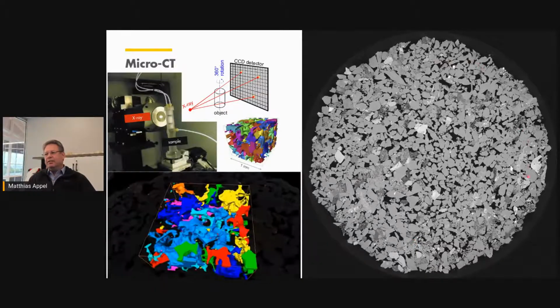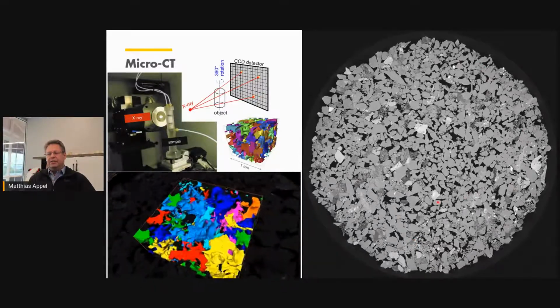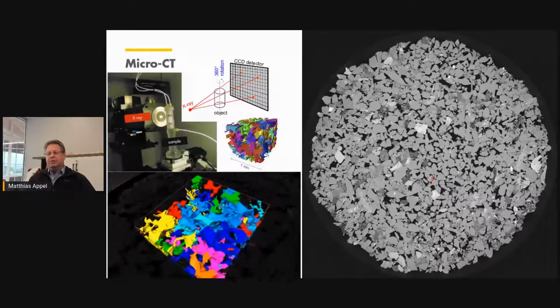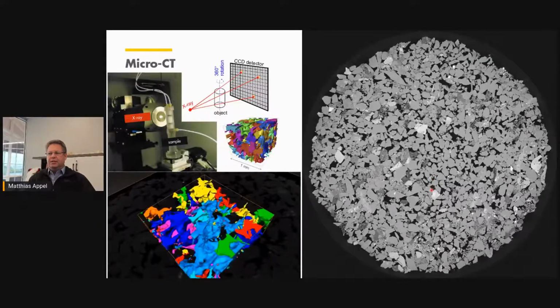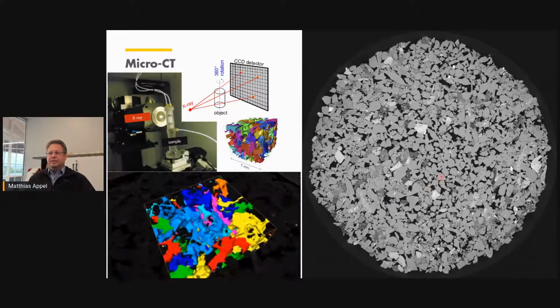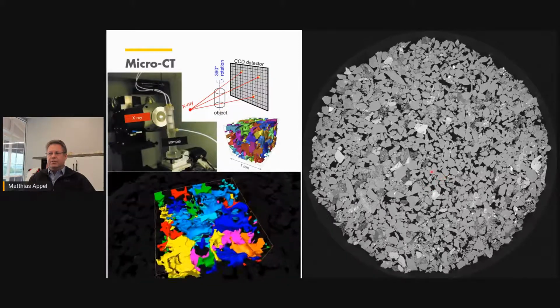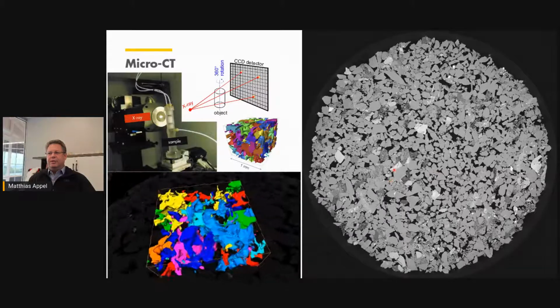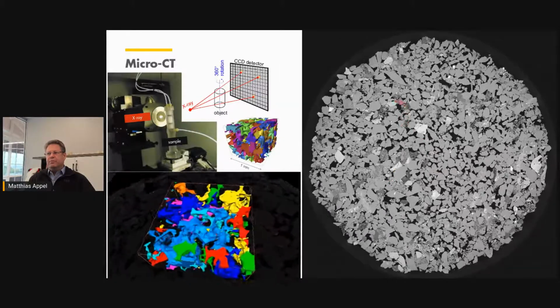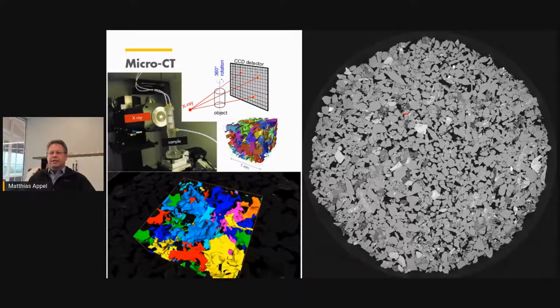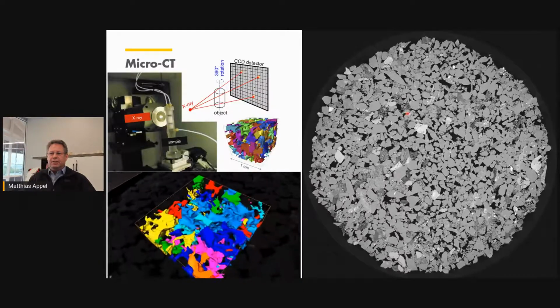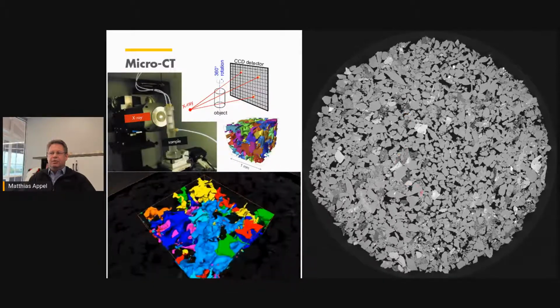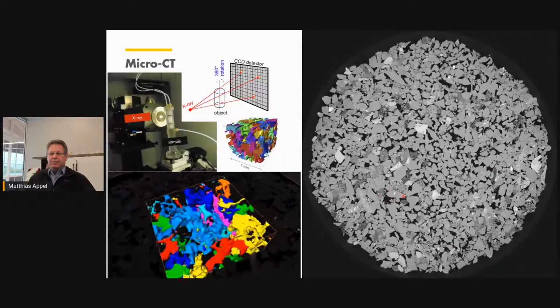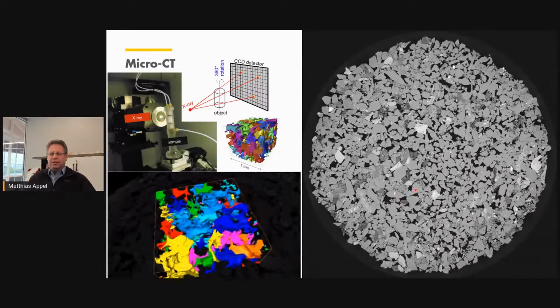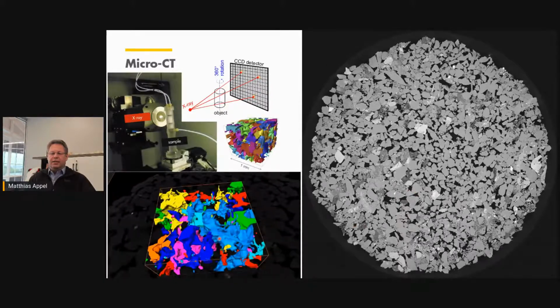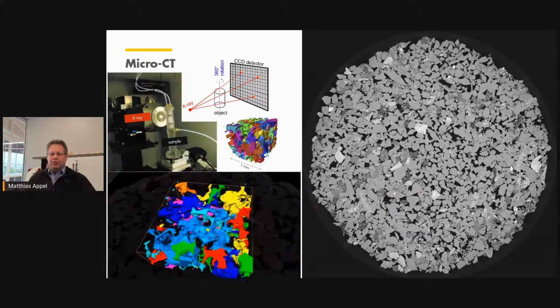What you see here on the right is just an example of the grayscale image of about 1 micron resolution sandstone. You see in black the pore space, the quartz minerals here in this gray color, feldspars, but also the clay structures here which have a certain microporosity. And with modern image analysis, you are able to not only segment these pore structures into the individual minerals, but also to compare how the pores are connected to each other.